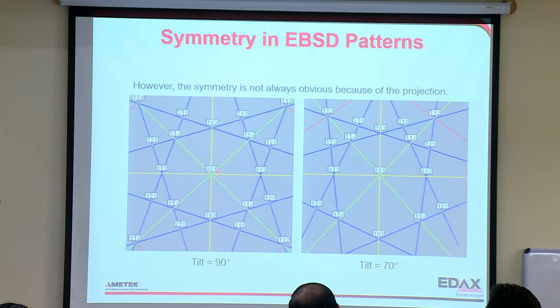So here's, for example, if my sample were tilted 90 degrees, my 001 would be nice and symmetric like you see here. But because we're tilted at 70 degrees, or somewhere near 70 degrees, you can see this is now distorted. And so the symmetry is not always obvious in the patterns.